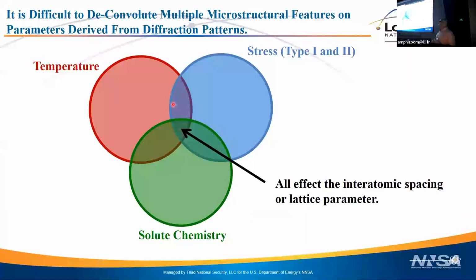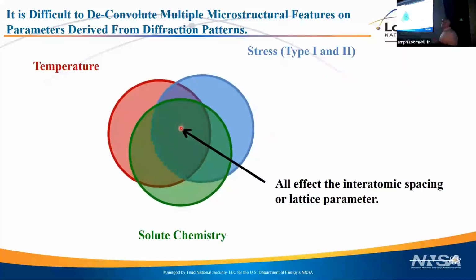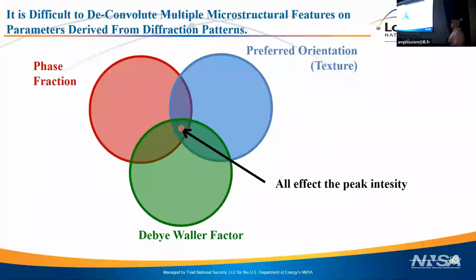And I've actually drawn this very much not in reality. It's not just a small area where these three intersect. It's actually almost the entire area of measurements that you're going to do have some intersection of these different microstructural features that all contribute to the lattice parameter. And the trick, in my mind, is being able to pull out, again, quantitative microstructural features despite that intersection of these. If you go to peak intensity, you have the same problem.